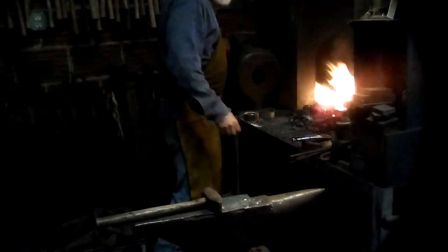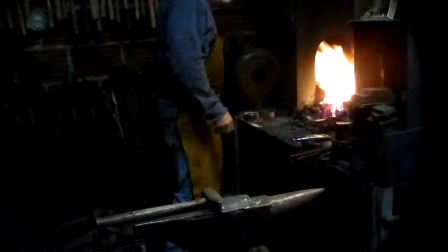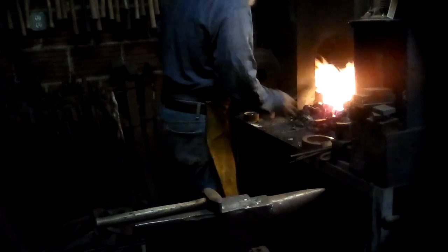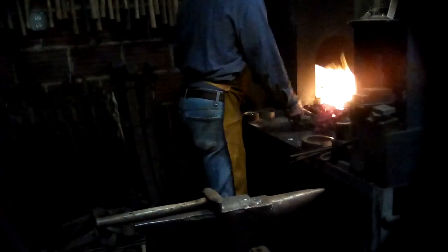Okay, so what I've done is I've taken that long billet that we just forged on the trip hammer, and I've taken off the iron bar, the helper bar, broken that off, turned it around, and I'm going to forge weld the slightly frizzy end that will be the tang. I'd originally thought of this billet as being something to make 3 of these Iron Age Norse knives. And now I'm thinking that I might want to get a couple of knives and a seax out of it, because this billet is big enough that I think I can get a nice seax and a couple of good sized knives out of it. So let's see what I can do.